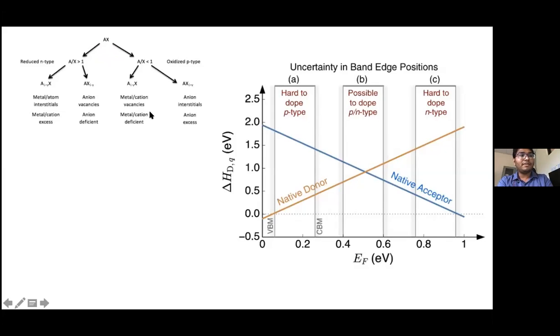The excess oxygen will have metal vacancies, which will give some acceptor level near the valence band maximum, and that would ionize at room temperature and donate holes, and we'll have excess hole carriers. On the other hand, if you have excess oxygen vacancies, which can lie just below the conduction band, at room temperature most of these are ionized, and they will contribute electrons to the conduction band, and you will have excess electrons in the system. Either way, if there are native donors like oxygen vacancies, it is very difficult to dope it p-type, because thermodynamically it likes to go into the oxygen vacancy state, which has the minimum free energy of formation. Correspondingly, you will have very high energy of formation for a metal vacancy, and correspondingly you will have no acceptor impurities, and if there is no acceptor impurity, you will not have any p-type conduction.